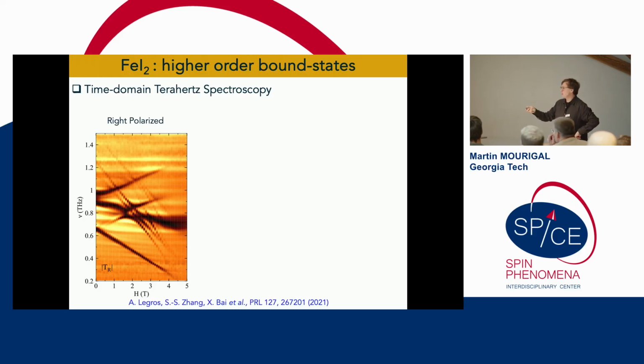And then we got regular spectroscopy in the end. So this is the Q equals 0 response of terahertz spectroscopy, with a terahertz magnetic field. And you see that at zero field, you have this single ion bound state, you have your magnon bands, but when you apply the field, you see that suddenly there seems to be a lot of complicated spectra here with a lot of lines seemingly coming from high energy.